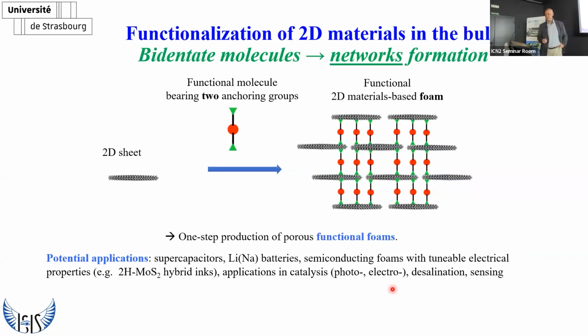You can also play with bidentate molecules. Bidentate molecules means that you have two anchoring groups, here in green, and in this way, you can tether adjacent nanosheets and create networks. And so you still have the red dot that is embedded in the molecule that has been designed, and you can add this new function that again can be used based on the dot you chose. It can be used for energy storage, for example, like supercaps or batteries, for tuning the electronic properties, for catalysis, for desalination, for sensing. It really depends on the design of the molecule that you choose.